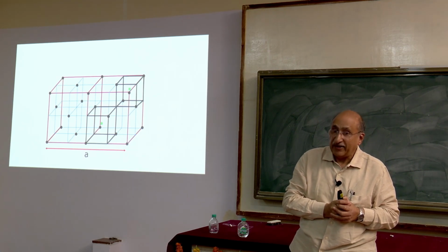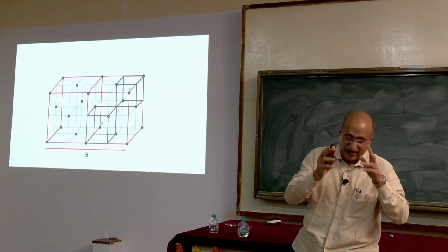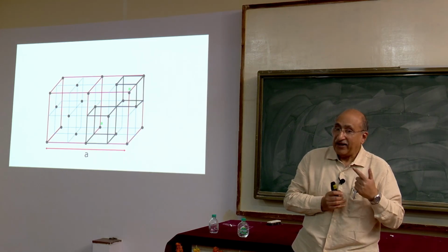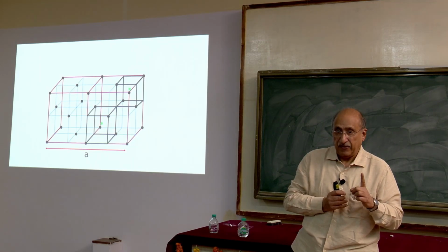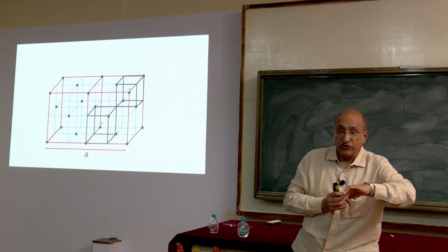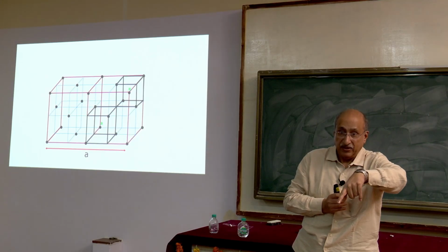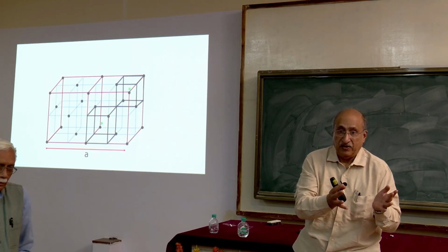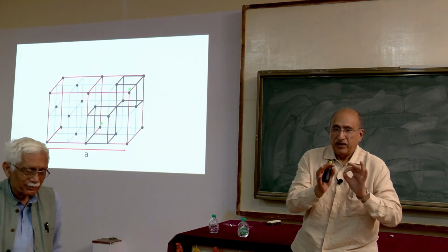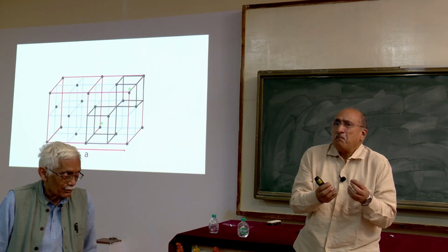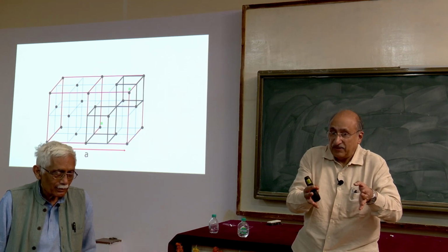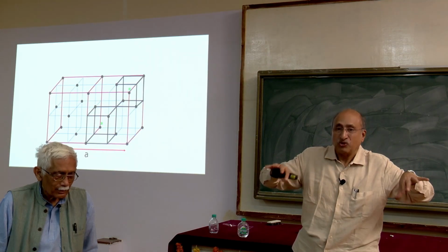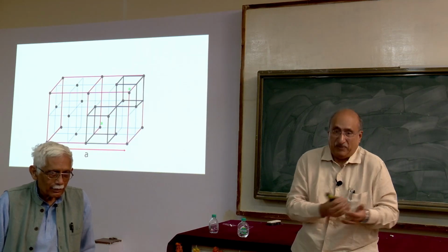For example, Fe3O4 magnetite is known to go to a monoclinic structure, I think it's monoclinic, I'm not very sure, when you cool it. Copper ferrite is supposed to show a tetragonal structure, and we have been able to freeze in a cubic structure by doing exactly the same thing. So there are some modifications which are possible, but the structures are known to be stable in some other form. To answer the question, maybe what you are saying is correct in certain sense, but that particular structure has also to be known to exist. It doesn't happen suddenly, randomly.